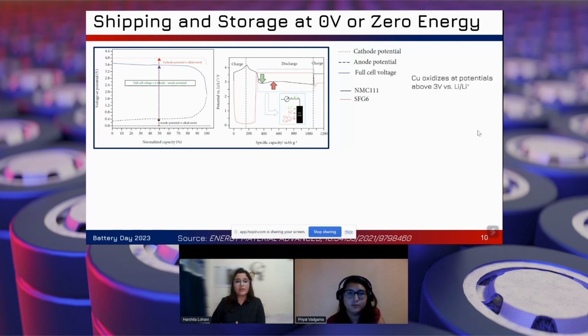However, for lithium ion batteries, if we discharge a full cell, the anode potential keeps on increasing, and when it reaches above 3 volt, copper oxidizes and starts coming from the anode side and depositing on the cathode side. So the performance of the lithium ion full cell degrades if we discharge it below 30% state of charge, or if we take it to 0 volt or zero energy.